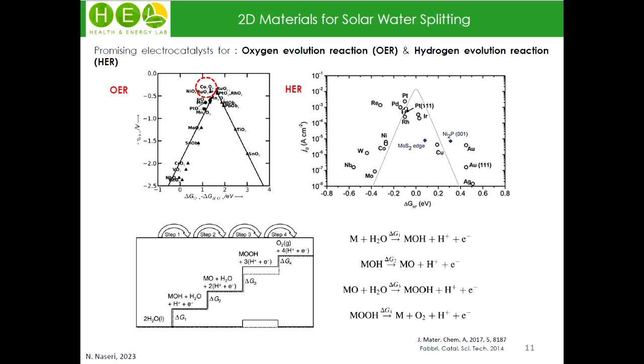As you can see, the most efficient candidates are expensive and precious, but we are looking for low-cost candidates. In terms of oxygen evolution reaction, cobalt oxide would be a very promising candidate, but it should be designed in a way that more active sites are provided on the surface, and the stability of the catalyst is also another issue.